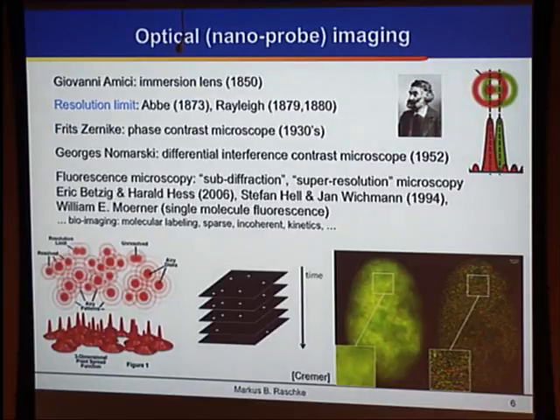Now, one problem with this technique is that it's not readily generalizable. It's hard to use for dense matter in particular, where you cannot simply label it and you would actually lose the function, which is the case in a lot of quantum materials and a lot of soft matter systems. And it's largely limited to fluorescence imaging, where it's extremely powerful if you have sparse emitters and can label a system, like in biological materials in a liquid environment.